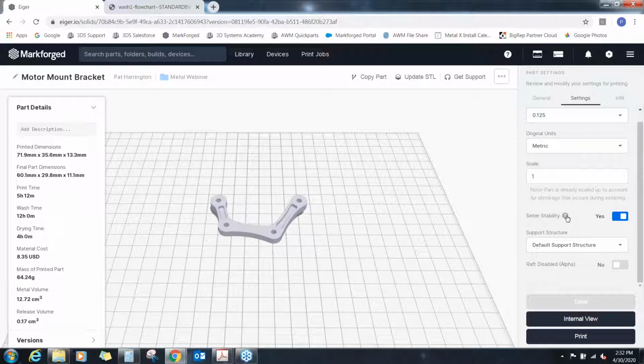So if you have a thin wall that is not an even multiple of 1/4 of a millimeter, what you would run into with the setting turned off is you're going to have gaps in between the beads that you place. And when those gaps get sintered, it's not going to bode well for the structural integrity of the part. So with the setting turned on, the software is smart enough to take those gaps in between the beads and actually fill it in with fully solid material so that you can be sure when this part goes through sintering, you're not going to have air gaps in your thin walls that will lead to strength issues going forward.